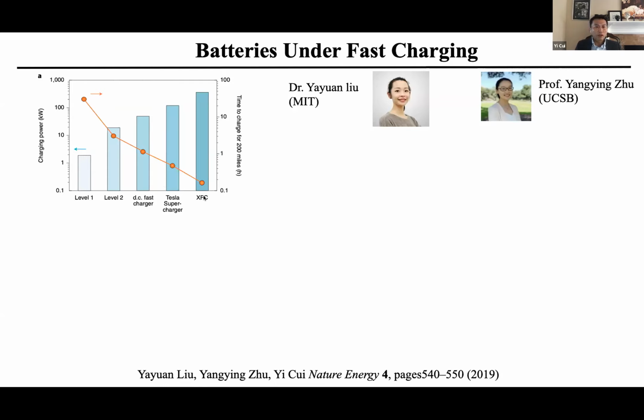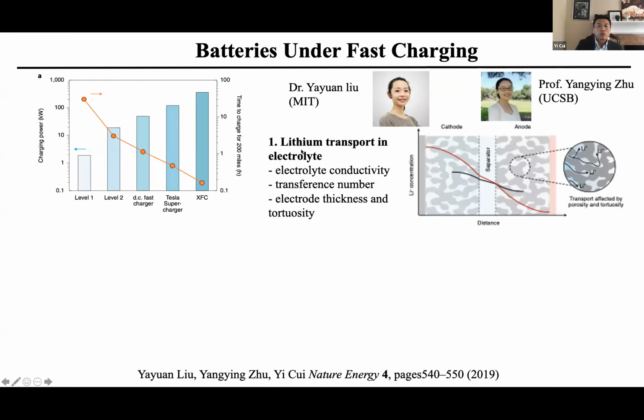Once you go to XFC, extremely fast charging conditions, you are really using power on the order of close to 300 kilowatts. Under this condition, there are many effects. The temperature can really affect the processes under fast charging. The first one is the lithium transport profile. During charging, the anode takes in lithium, and the lithium ions come out on the cathode side. So you build up this concentration gradient.